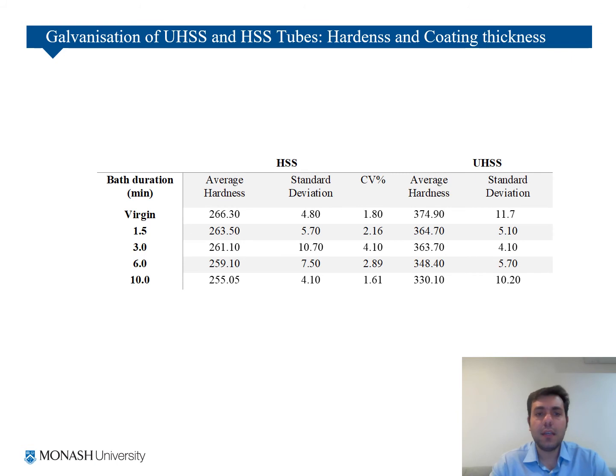And we found that actually the hardness of materials for high strength steels did not change much, but for ultra high strength steels, after galvanizing for 10 minutes, the hardness dropped around 10.